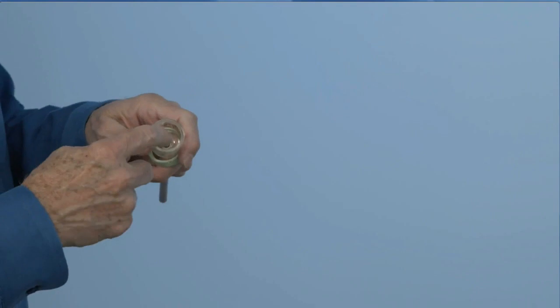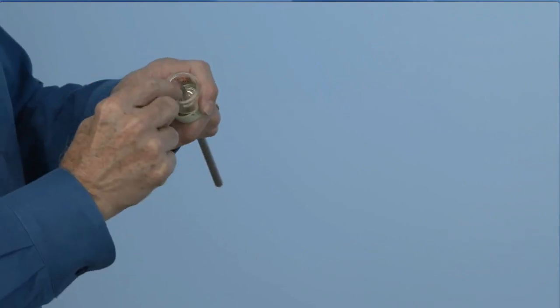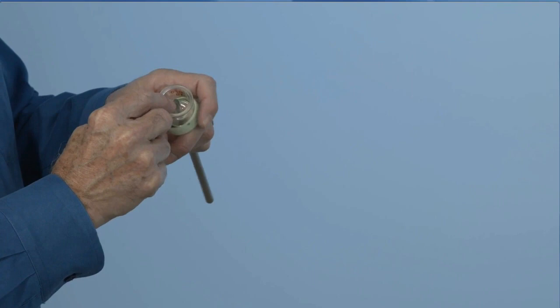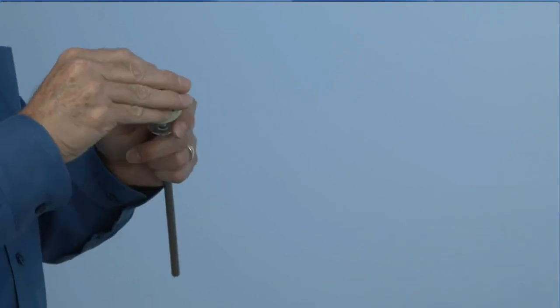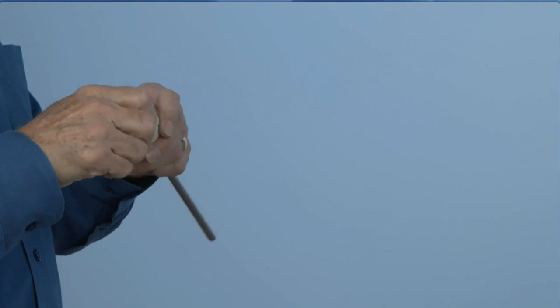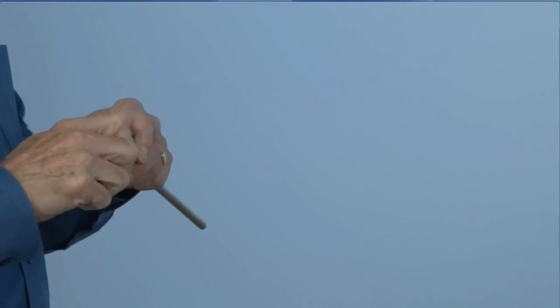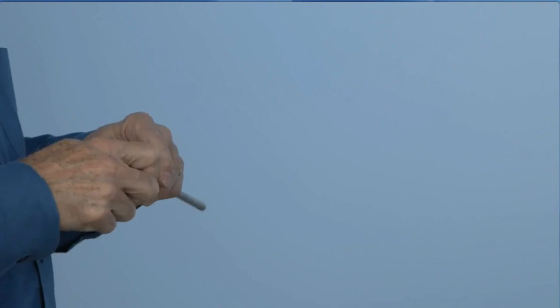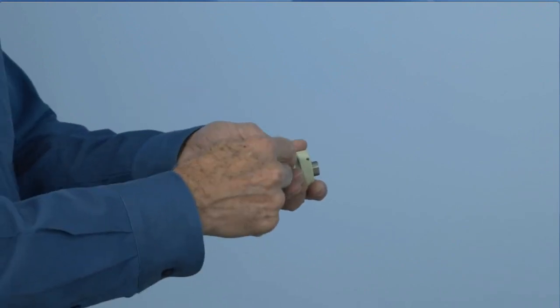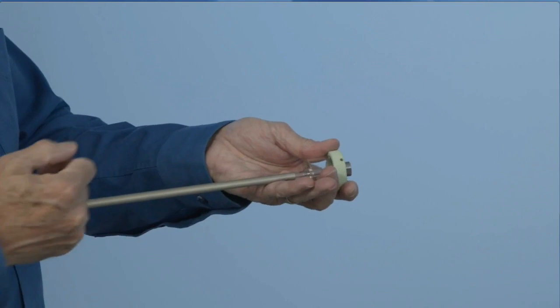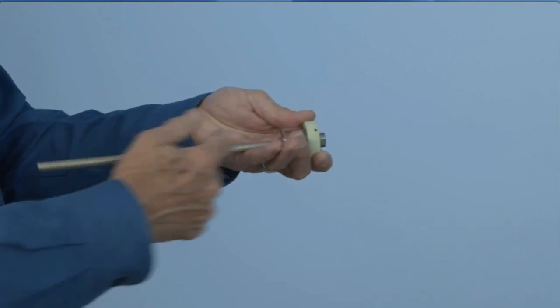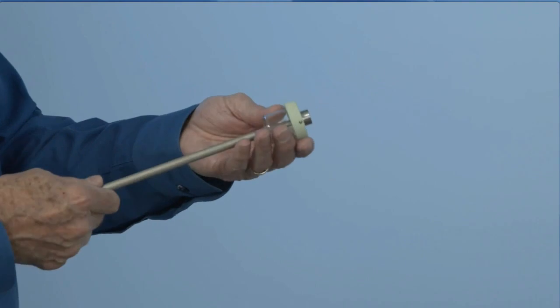And then finally, this is a 15 cubic centimeter one. All of these come as both solid and powder type penetrometers. This one happens to be a powder again, with a much larger capacity here. So again, we have penetrometers to meet the size needs and the porosity needs of a variety of samples. Now, to the instrument, it really doesn't matter. We have to give it some information about the volume of the penetrometer when it's empty, and which of the stem capacities we're using, so that it can convert capacitance into volume. Otherwise, they all work pretty much the same, and they're all loaded pretty much the same into the instrument.